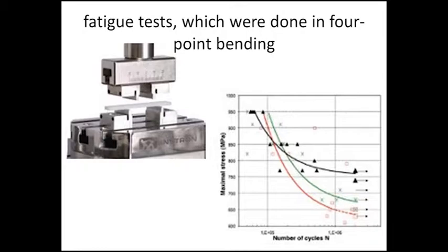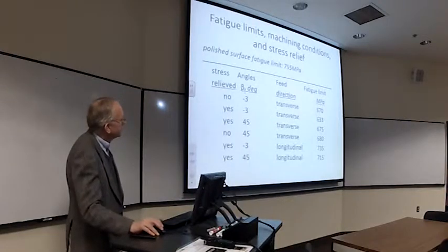The fatigue tests were done in four-point bending. There were about 80 fatigue specimens that were used to establish the fatigue limits for the six different cases. And so here are the fatigue limits. Just the polished surface has a higher fatigue limit than these. So there's a nice range of fatigue limits.